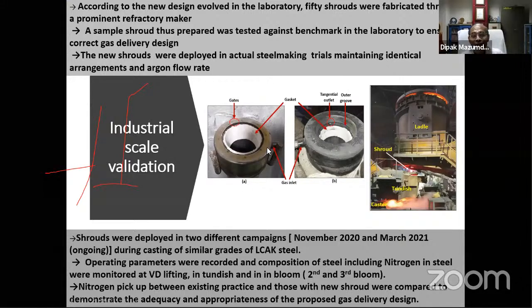So we found a refractory manufacturer who was willing to make this refractory artifact, the ladle shrouds. We found a steel plant which was trying to minimize their atmospheric air absorption through ladle shrouds. So they are also keen to incorporate this shroud design. So we made about 50 shrouds, brought them to our laboratory first, and then we wanted to be sure that they could incorporate our design precisely. Having given the final clearance,